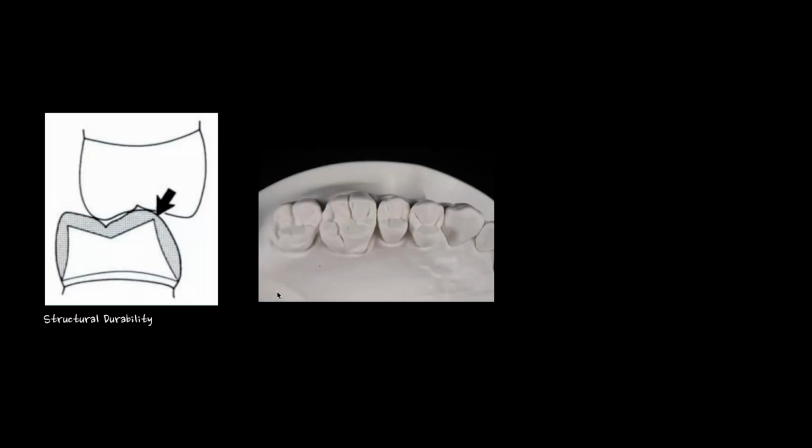The other little challenge that I do see with some of the minimally invasive, especially in the posterior, obviously in the anterior it's aesthetics, in the posterior it's function. And what I see here is that because we're trying to minimally invade our preparations, you're leaving what I call danger spots. And these danger spots are the areas where no matter what material you are, monolithic or layered, this is a spot where the doctor did a ton of reduction on the axial wall, but not enough reduction in the third plane. And yes, molars have three planes too, just like the anterior teeth do.